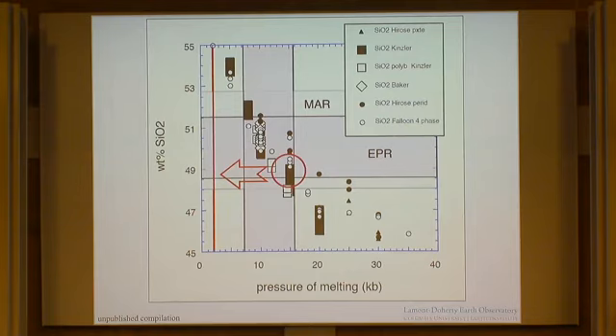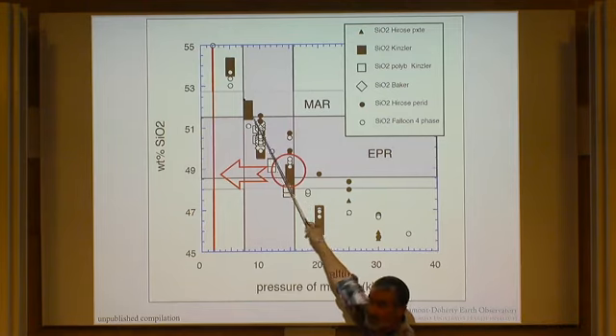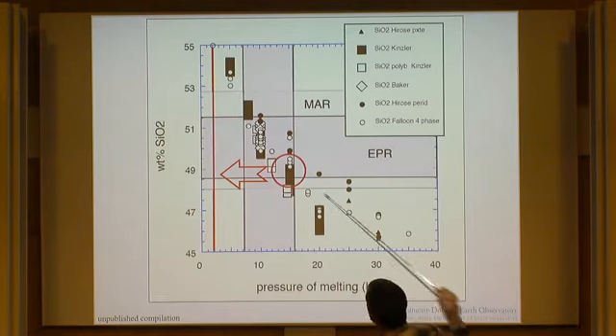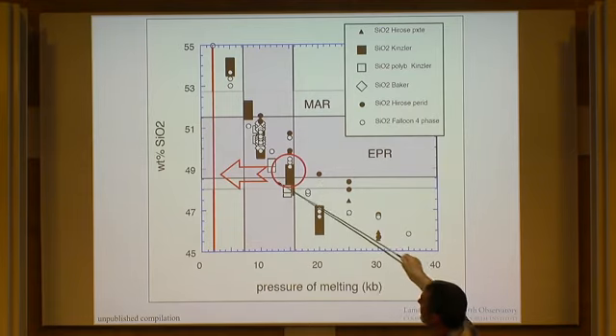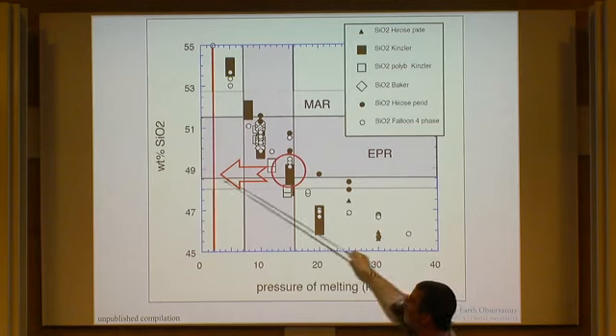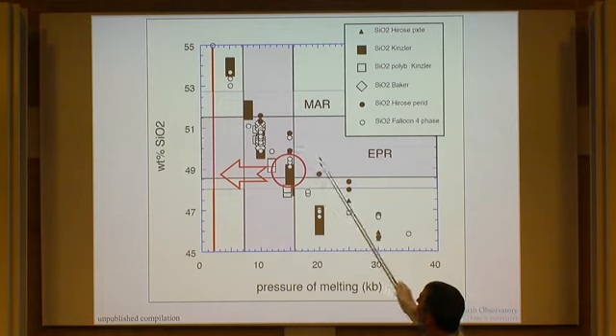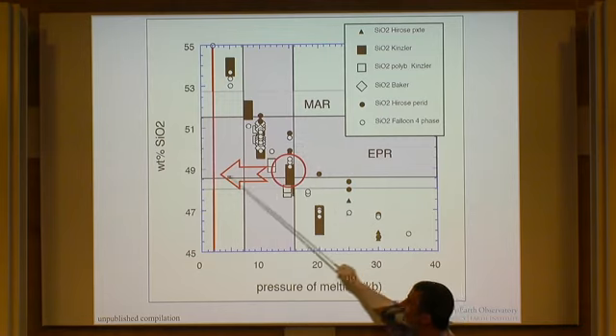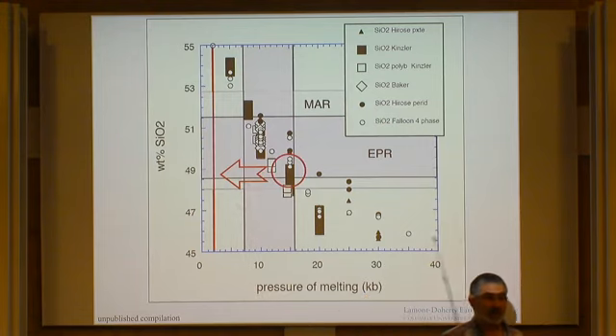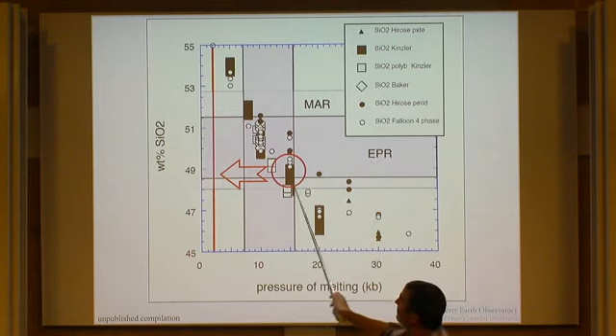The magical thing about mid-ocean ridges that determines the composition of the oceanic crust is that, in this sweep of silica contents of melts in equilibrium with the mantle at different pressures, the mid-ocean ridge basalts sample this relatively low silica, 49% silica type composition dominantly, particularly at the East Pacific Rise. So we see this very homogeneous stuff coming out, and it seems to record an average pressure of melting somewhere in the neighborhood of 1.5 GPa.